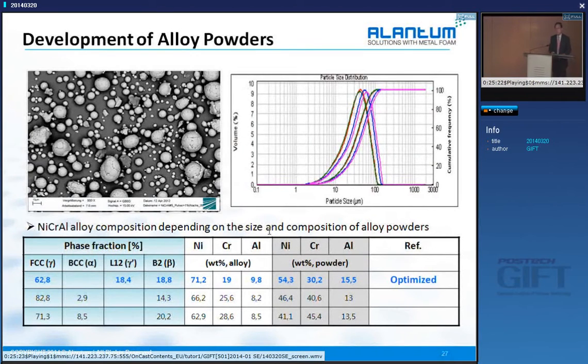You can ask me then, you mentioned that alumina is a very good layer, so why don't you add more and more aluminum? But once you have more aluminum, this material becomes brittle, okay? So that means we need some kind of optimum contents. Chromium helps ductility. But if you add more chromium, later on for the catalyst, the chromium migrates onto the surface of the platinum or PGM materials. It's the so-called contamination problem. So that's the reason we need some kind of optimization.